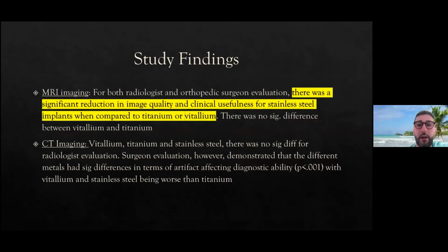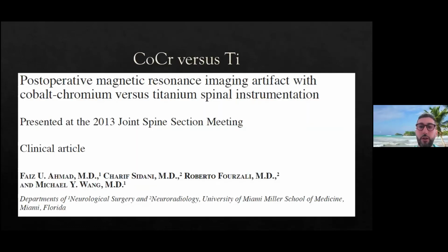And so basically, what did they find? For MRI imaging, there was a reduction in the image quality and clinical usefulness for stainless steel when compared to titanium or vitalium. Again, another reason stainless steel has fallen out of favor. And when it came to CT imaging, there's no significant difference for radiologist evaluation. However, on surgeon evaluation, there were significant differences between metals, with vitalium and stainless steel being worse than titanium. And again, if nothing else, you begin to understand why certain implants have become more favorable and others have become less.